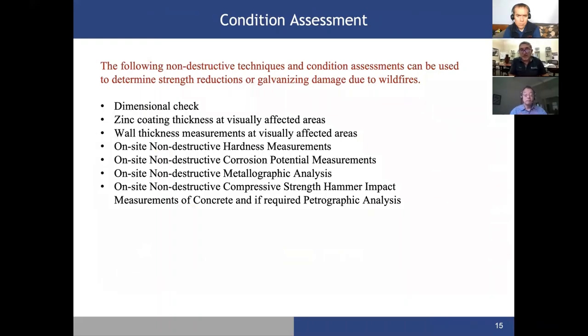So what should we do on condition assessment? The question that you ask. We should perform dimensional check, zinc coating thickness measurements, wall thickness measurements, non-destructive hardness measurements that can give us information about mechanical properties, and corrosion potential measurements. Sometimes we need to do metallurgical on-site investigation. These are all non-destructive. And on the concrete foundation, we need to do compressive strength hammer impact test measurement to see if more detailed work, more direct assessment of concrete by petrographic analysis, is needed.